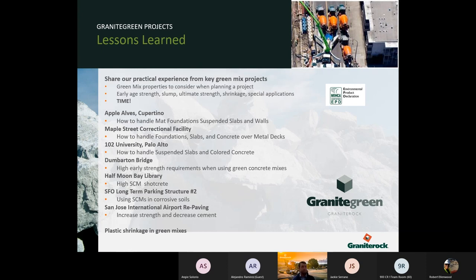Half Moon Bay Library, the spec wanted a 50% replacement in all concrete, including shotcrete. Shotcrete is basically when you use high pressure to blow concrete onto a vertical surface. However, with less cement, the shotcrete wasn't able to stick as well as a more heavy cement mix.